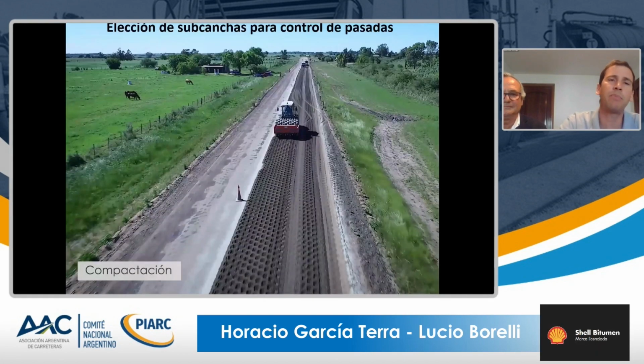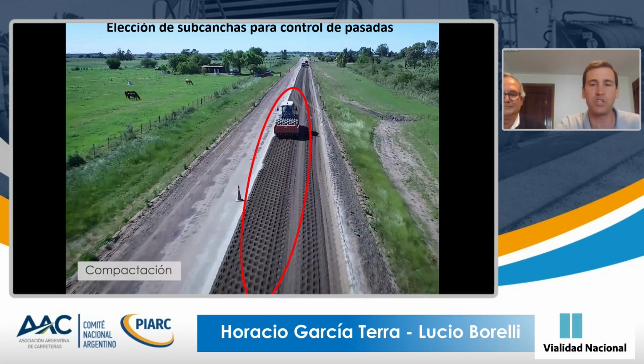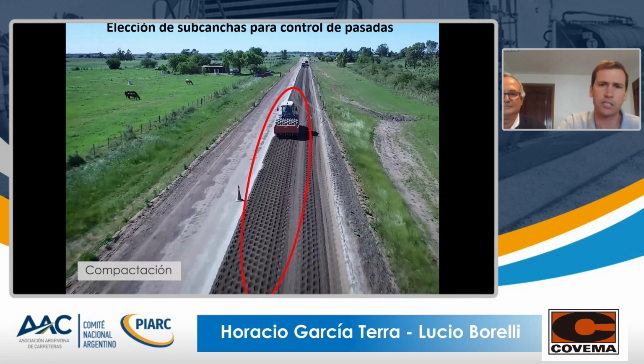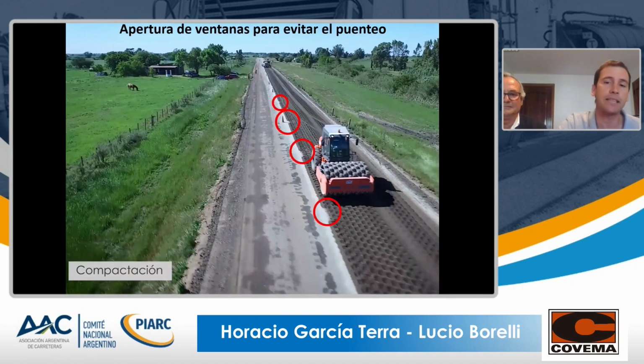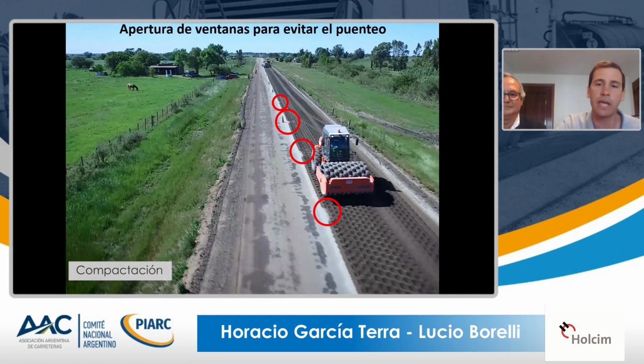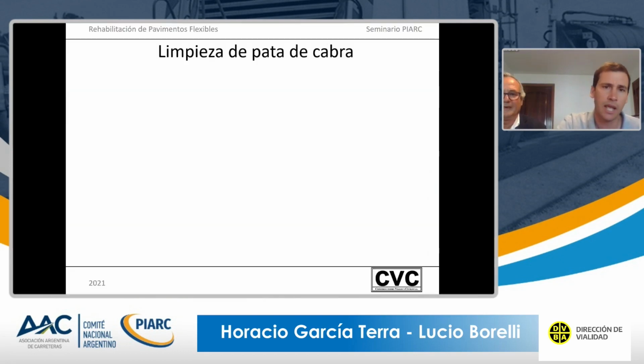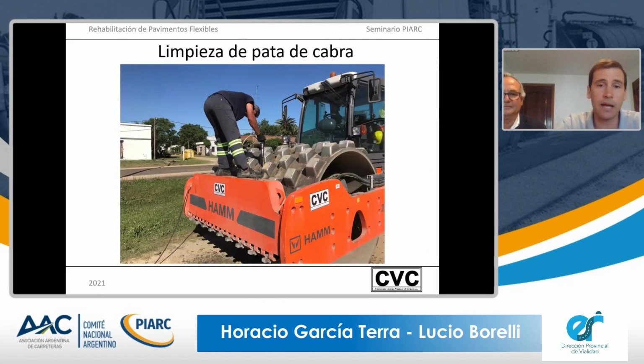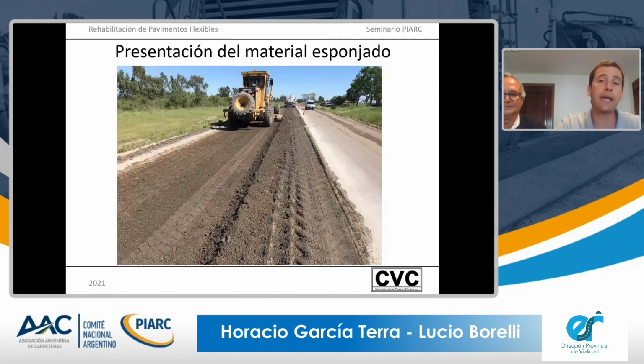This is very important. As to compacting, the truck driver should choose the stretches for passing the compacting machine, maybe 7, 9, 8 passes. But in this case, the driver must choose up to what extent or what is the stretch to do the passes, and then to go back. And the driver needs to have a guide in order to be able to compact the whole thickness of the recycling stretch, and this is very important. We need to clean the roll of the truck there, because if not, it loses its property.